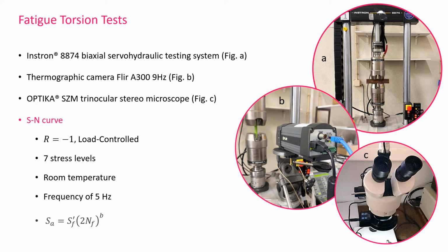The optimized set from monotonic torsion tests was subjected to cyclic torsion loading conditions to study the fatigue performance of these components. To accomplish this, Instron 8874 biaxial servohydraulic testing system was used and it is shown in Figure A. To avoid heating, temperature was controlled with a thermographic camera FLIR A300, shown in Figure B, and Optica SZM trinocular stereo microscope, shown in Figure C, was used to evaluate specimens' fractured surface.